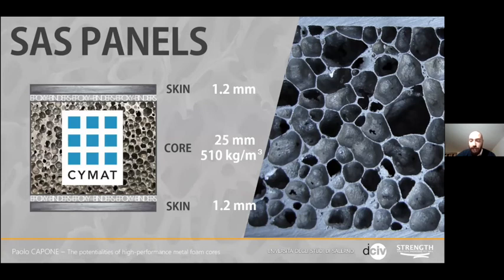The SAS panels have been realized with two thin steel skins of 1.2 millimeters and an aluminum foam core of about 25 millimeters. The density of the core is 510 kilograms per cubic meter. It is bonded to the steel skins testing multiple epoxy binder solutions. The aluminum foam used to realize the panels is produced by Cymat Technologies in Canada.